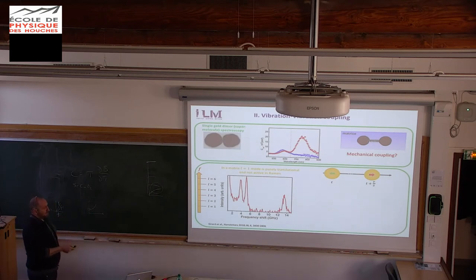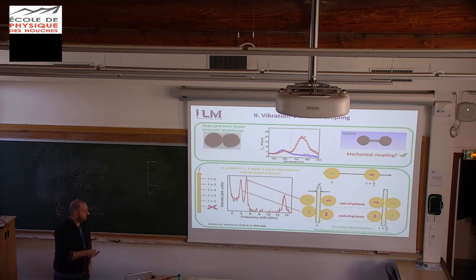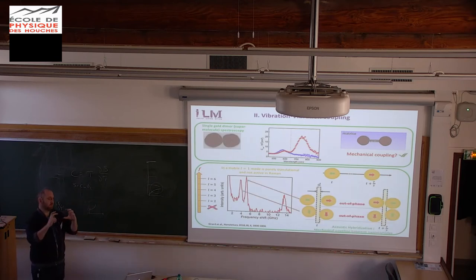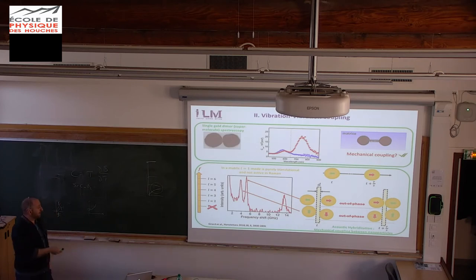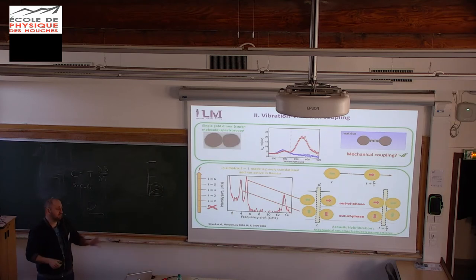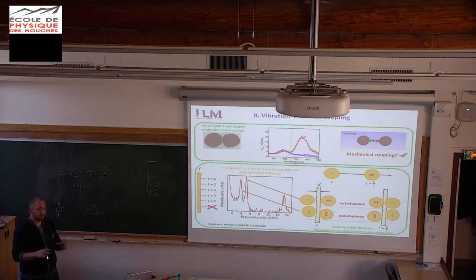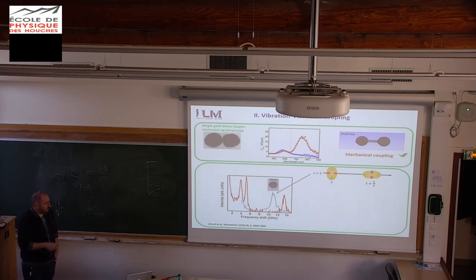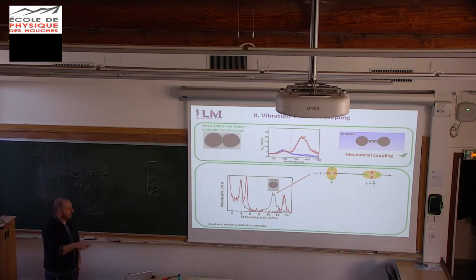But we are not looking at a single nanoparticle. We are looking at a dimer. And in that case, if the two nanoparticles are translating in phase opposition in two directions, you can explain these results. So these two peaks are due to the acoustic hybridization. Due to the presence of the matrix, there is a mechanical coupling in between those two nanoparticles. And what you are seeing is this. And this acoustic hybridization not only happens for this L equal 1 mode, but also for L equal 2 mode.